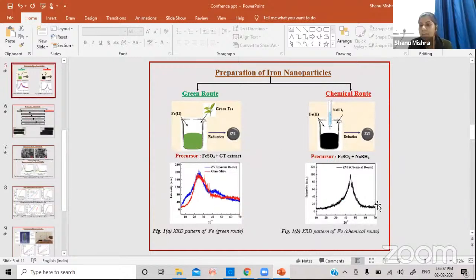Yes, ma'am. Actually, for iron nanoparticles, from the literature we know that they have a peak at 45, and we are seeing a peak at 45 here. I also plotted a glass slide peak here, because when you have an amorphous nature, the peak of the iron nanoparticle is quite low due to the small particle size. In literature, we have seen this; I would have to show some images for that, but the presentation had only 8 minutes, so I haven't included it here. We can see from the sample that the particle size is quite low. That's why we have an amorphous nature and this broad peak, but it still has the 45 peak, which confirms the formation of zero valent iron nanoparticles. Okay, thank you.